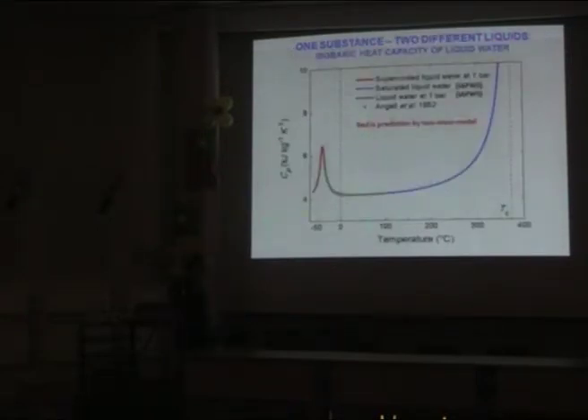Next slide. Especially if you look at the heat capacity at constant pressure, it is also a dramatic picture. You have, of course, divergence of the heat capacity, together with compressibility, near the liquid-vapor critical point, but you also have apparent, or at least possible, almost divergence, or at least a very sharp peak, of heat capacity at low temperature in the liquid phase. So this picture opens the way to speculation that maybe the entire liquid state of water is just a narrow domain between two critical points. One is the liquid-vapor critical point at high temperature, and the other some kind of critical point at low temperature. Next slide, please.